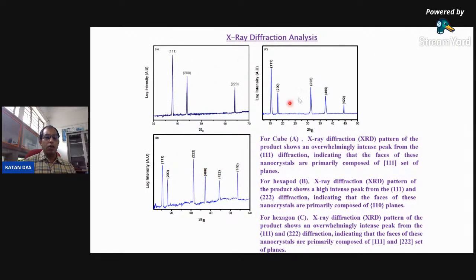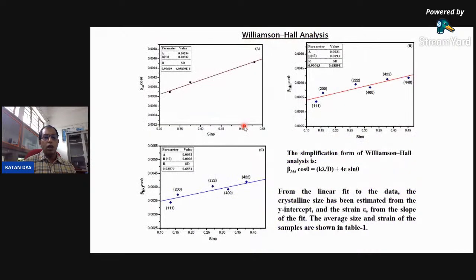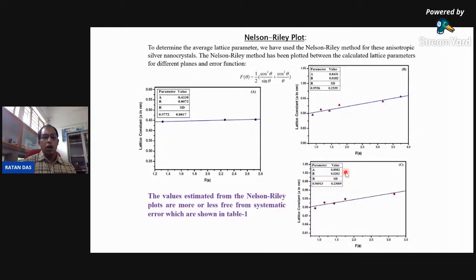So these are some XRD diffraction patterns of our samples, which we have analyzed and published. This is related to silver nanocube, silver nanohexapod, silver nanohexagon, etc. And there are some Williamson-Hall analyses through which we can obtain the epsilon, what is called intrinsic strain. There are some techniques that there is no scope to discuss here. And there is a Nelson-Riley plot, through this plot we can obtain an error-free lattice constant. I want to say that through XRD analysis we can obtain all these parameters.